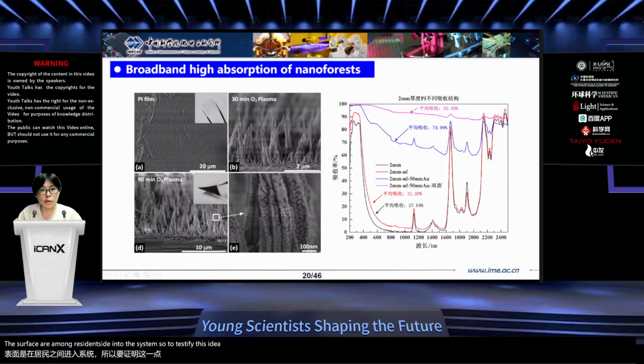As we know, silicon-based nanoforests exhibit excellent broadband and high absorption features due to their surface effect, size effect, and light trapping effect. Such a structure is sometimes known as black silicon. However, restricted by the band gap width of the material, the absorption rate of the silicon nanoforest decreases significantly when the light wavelength is larger than 1.1 micron. In order to broaden the high absorption band, we propose a method to introduce surface plasmon resonance into the system. To test this idea, we used a transparent flexible substrate. We prepared the nanoforests on both sides of this substrate and introduced gold nanoparticles on the nanoforest with a thickness of about 30 nanometers.